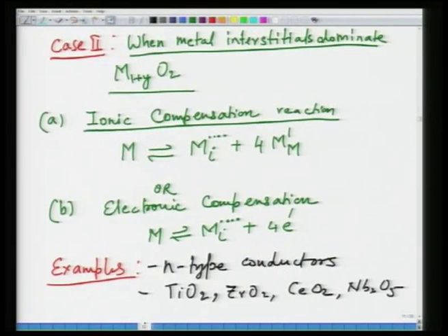And then we looked at the case when metal interstitials dominate, and in that case, for example, we have taken MO2. So, here it would be M_(1+y)O2, and since the metal is 4+, the metal will form an interstitial complemented by reduction of metal on the metal site, or if it was electronic compensation, then it would give rise to 4 electrons. So, the difference in the two cases is the number of electrons created and the relative proportion of the two defects. Examples of such cases could be n-type conductors, materials such as TiO2, zirconium oxide, cerium oxide, Nb2O5.